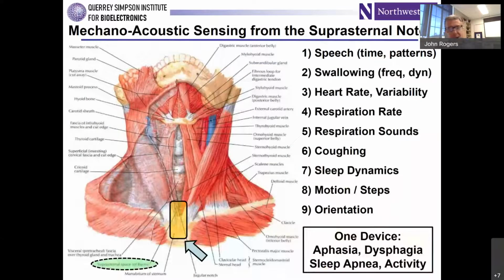And so these devices mount on the base of the throat, and you can capture vibratory signatures of speech. You can measure motions associated with swallowing. You're also close enough to the carotid artery, you can pick up signatures of cardiac activity, so you can get heart rate and heart rate variability. You're coupled to the top of the chest wall cavity, so you can get motions associated with respiratory cycles, but also respiratory sounds, coughing, sneezing, wheezing, this kind of thing, body orientation, motion, steps, and so on.